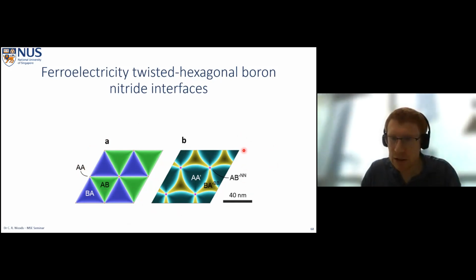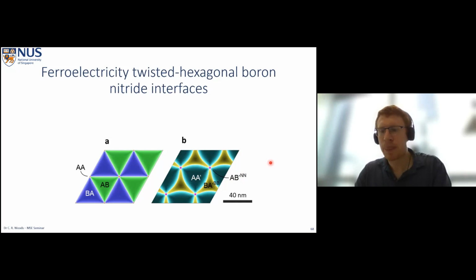This contrasts to the anti-parallel case, where AA prime is the most energetically favorable, and we would expect to see hexagonal unit cells to our superstructure, where both BA and AB are less energetically favorable than AA prime. So this can really just maximize its area of the interface.